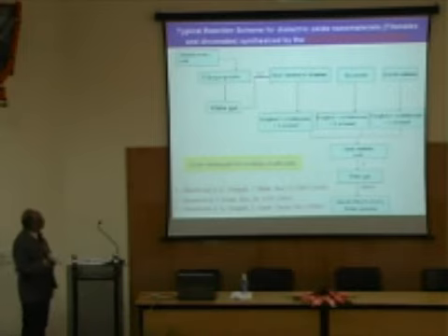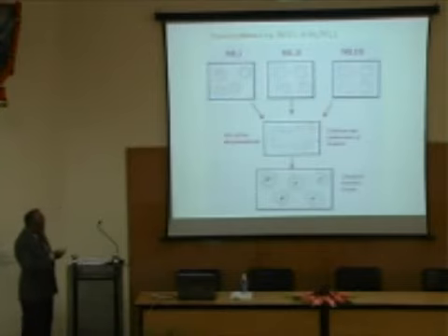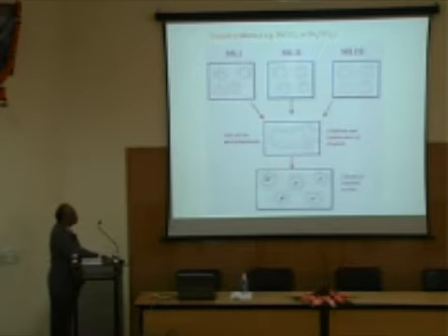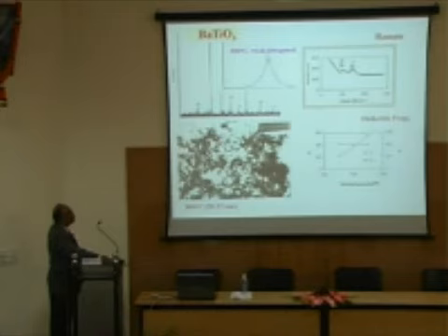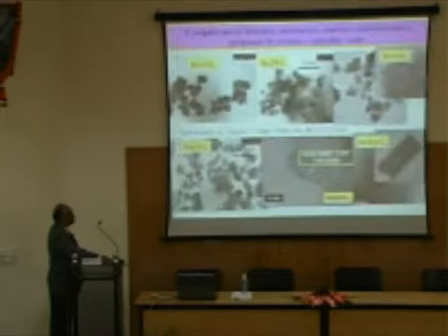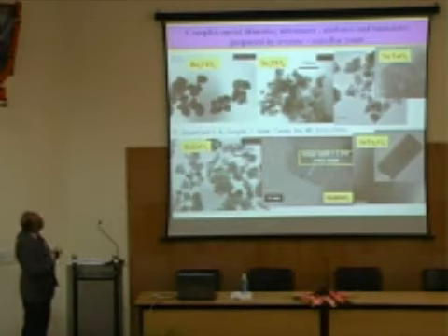We have done a lot of work on making nanostructured dielectric oxides using microemulsions, which are also called reverse micelles. We have developed some procedures by which we can get these nanoparticles. Earlier I showed you two microemulsions; now you need three microemulsions because you have barium, titanium and oxygen. So there is a protocol to be developed for how you get these particles, and then you look at them in the TEM, etc., to prove they are nanoparticles, and like that we make a host of others.